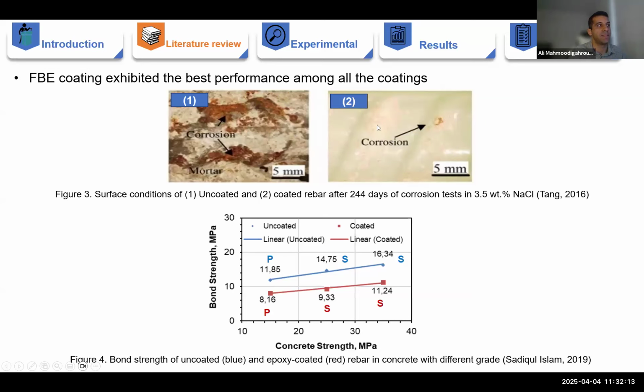which is related to maybe pre-existing damage on this sample. And basically, it doesn't matter for rebar corrosion because the type of corrosion in concrete is localized. So it doesn't matter if you have a large surface area like figure number 1 or you have a tiny spot. The damage is going to be the same.